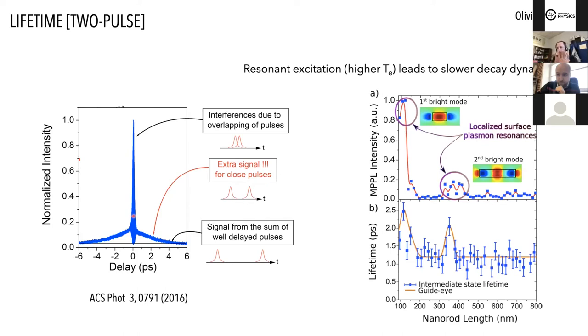But what's interesting is that when you start to have a delay between the two pulses, you have a non-zero nonlinear photoluminescence signal, which is still generated, okay, which eventually goes to 1 when the two pulses are strongly separated. And this is basically a measure of the lifetime of this signal. So it's a very convenient way to estimate the lifetime.